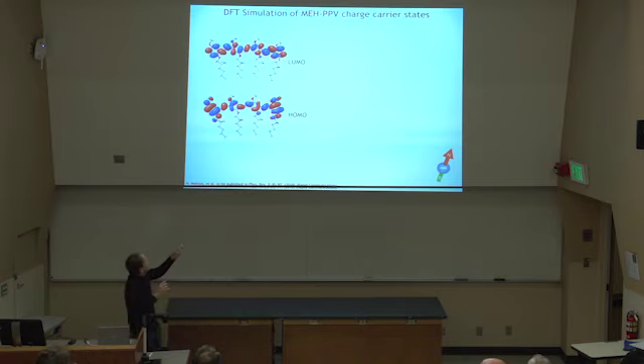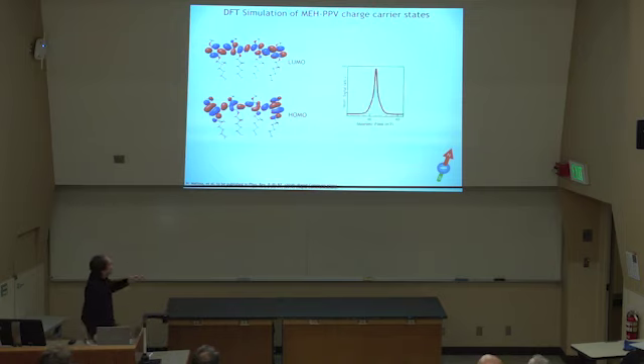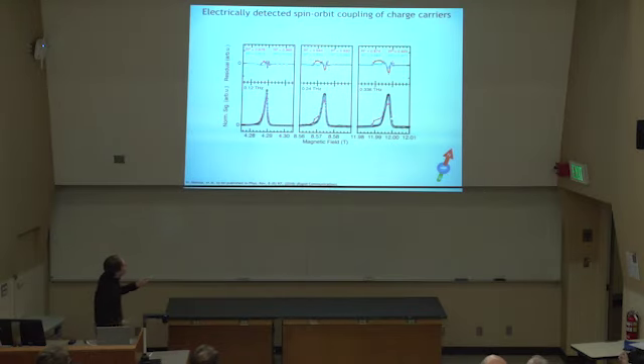So we take the g-strain, basically the spin-orbit mediated effects on our resonances, and make predictions. We take calculations, not fit our data; we calculate our data based on these predictions. And we also take hyperfine fields that we measure at low magnetic fields and plug them in there. So we combine it with experimental data that is corroborated, and then we just compare.